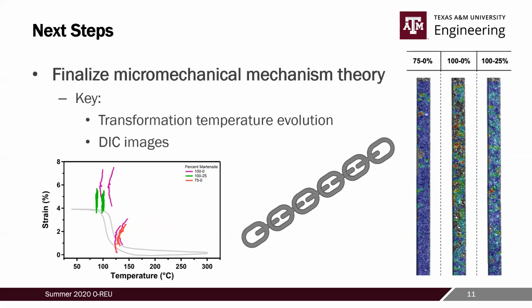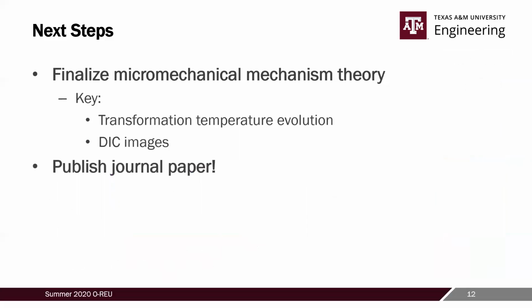So in the DIC images, we can see that some samples have very localized strain, while some have strain more evenly distributed throughout the sample. And these are all important things to consider as we develop a theory, and in the discovery process, we may find that we need to run a couple more tests to complete our study. Then finally, after all of that is done, we will hopefully have what we need to publish a journal paper on partial cycling with nickel titanium hafnium.